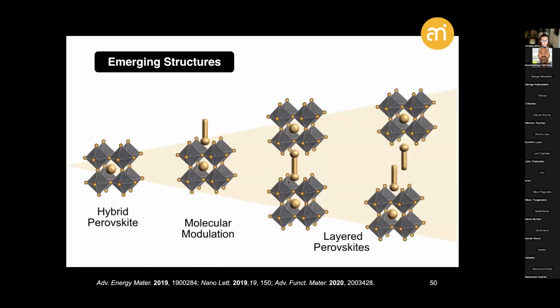which are relevant in the context of these molecularly modulated samples, but even more so in lower dimensional or layered perovskite architectures, where now the organic component serves as a spacer layer templating the inorganic perovskite slabs in the manner that either involves this bifunctional organic monolayer with the well-aligned inorganic slabs in the so-called Dion-Jacobson or DJ perovskite architectures, or such monofunctional organic bilayers, characteristic for more common Ruddlesden-Popper or RP architectures with a slight half a unit cell offset between the inorganic phases.